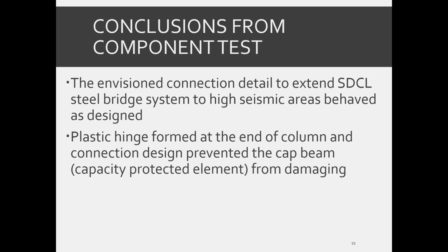So one conclusion, as the experimental test indicated, is that the connection detail that we have come up with for extending the SDCL to the high seismic areas is working, in the sense that it made sure that the capacity protected portion of the structure remains elastic. As Amir mentioned, the maximum strain in the vertical bar in the cap beam was just 800 microstrain. In the deck, we had about 200 microstrain, way below the yield, while the plastic hinge was forming at the end of the column. So in that sense, the connection did its job, kept the cap beam pretty much elastic. And the plastic hinge, of course, formed at the end of the column as we expected.